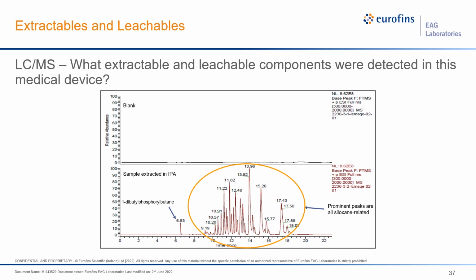Looking at some LCMS data, again, we have a method blank, and then we have our sample that was extracted in IPA. Again, after analysis, we see that all these prominent peaks are all siloxane related, which again is going to be consistent with our FTIR as well as our GCMS findings. But we also see this other component, 1-dibutyl-phosphoryl-butane. We'll discuss this a little bit more in the next slide.